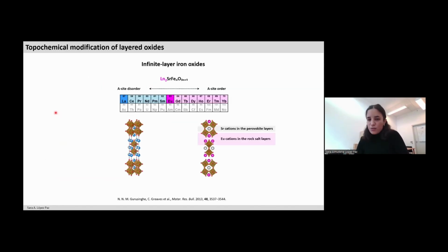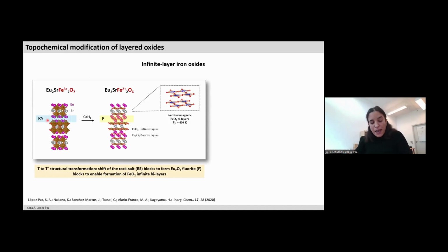What if we try to introduce some cation order on our precursor? And this is something that we can actually do if we replace part of strontium by a lanthanide. For certain sizes of the lanthanide ion, we can get a layered order of these A-site cations. And then when we try to reduce this ordered compound, what we observe is that the rare earth or the lanthanide layers actually undergo a structural reconstruction to release the strain that they have in this mismatch and go from a rock salt to a fluorite configuration, and they leave behind a pair of two infinite layers of iron.